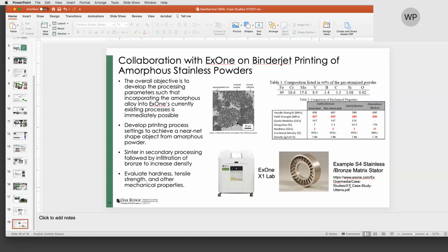Compared to this, where we're looking at a stainless steel, we've shown that you can get about a 5 times increase in the hardness values of the material as we start thinking about using something like these nanocomposite materials. Just one example of a hybrid structure that you could utilize. It is a powder bed. It is not, though, looking at it specifically for graded structures, which obviously directed energy deposition, some of these others make perfect sense. But just wanted to share that as an example. I don't know how to stop sharing, sorry.